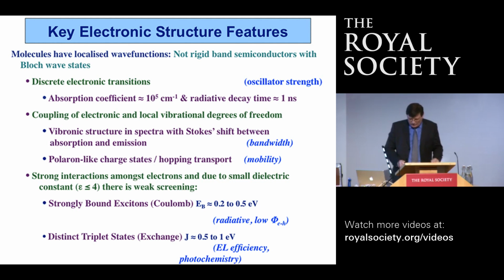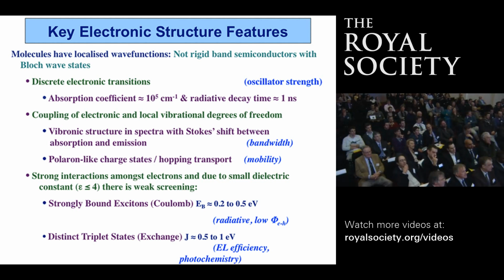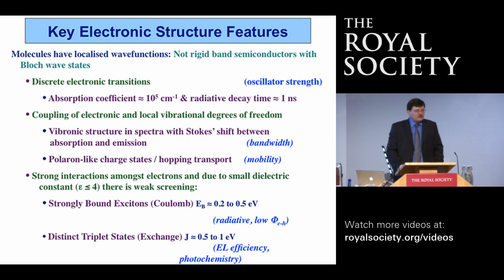And there are many consequences that follow from that localization. Firstly, we have very strong absorption coefficients. What does that mean? It means that the materials we work with are very strongly colored. So a thin film of these materials absorbs a lot of light and has a bright color. We don't need a large amount of material to absorb the light. And typically, the absorption coefficient is about 10 to the 5 per centimeter, which compares to about 10 to the 3 per centimeter for something like silicon.